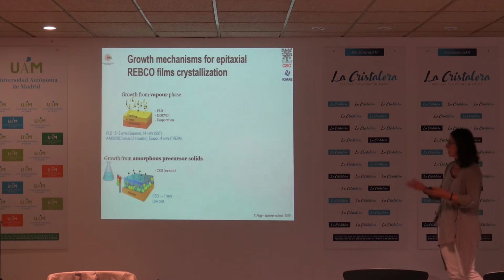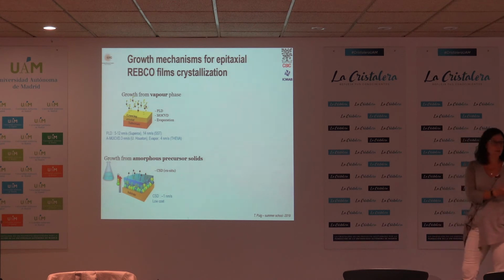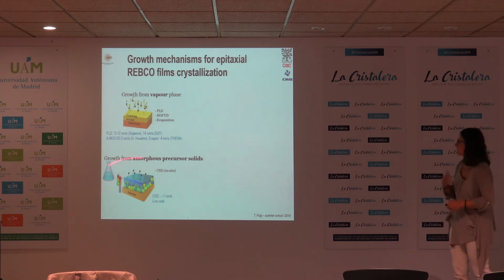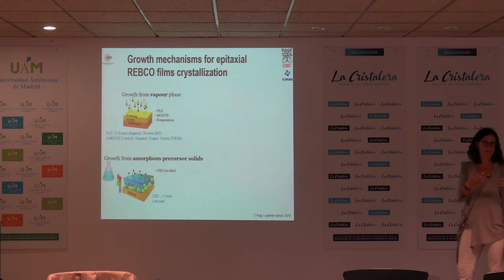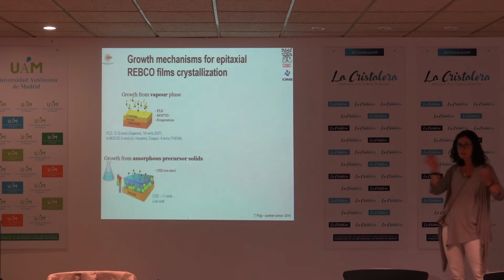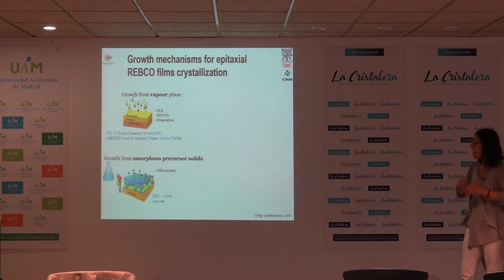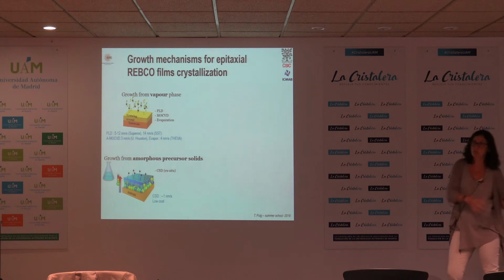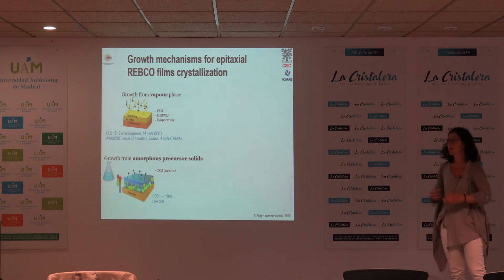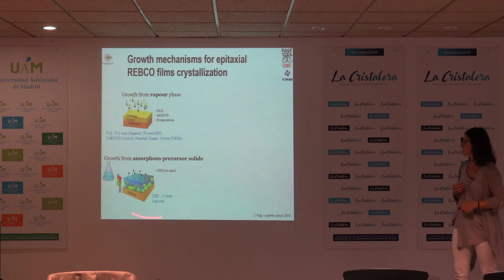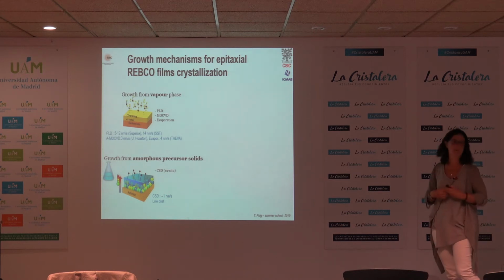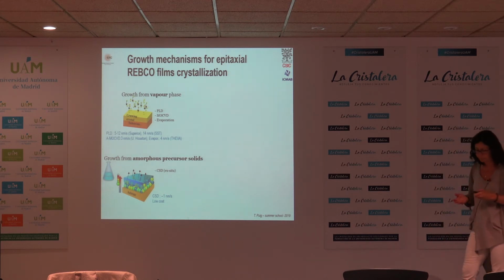If you grow from a CSD, from chemical solution deposition, after the decomposition of the organic, after the pyrolysis, you end up with these nanoparticles, yttrium oxide, copper oxide, and so on. And then from this solid, you have to go to another solid, the YBCO. And this is really a slow process. It's a solid-solid reaction of the order of 1 nanometer per second.